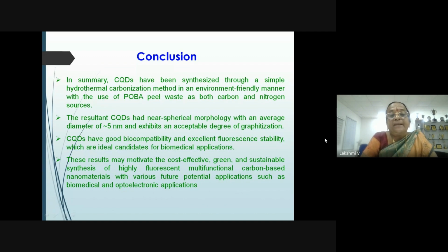So my conclusion, in summary: CQDs have been synthesized through a simple hydrothermal carbonization method in an environment-friendly manner with the use of POBA peel waste as both carbon and nitrogen sources. The resultant CQDs had near spherical morphology with an average diameter of approximately 5 nanometer and exhibit an acceptable degree of graphitization. CQDs have good biocompatibility and excellent fluorescent stability, which are ideal candidates for biomedical applications. These results may motivate the cost-effective, green, and sustainable synthesis of highly fluorescent, multifunctional carbon-based nanomaterials with various future potential applications such as biomedical and optoelectronic applications.